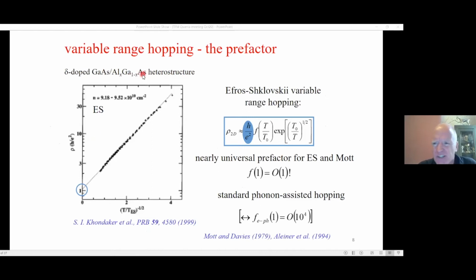And just a little bit more detail on that. If we're in this Efros-Shklovskii regime, and we normalize the temperature to the characteristic temperature for each carrier density and then plot them out, they have a universal behavior. They all fall on the same line. The intercept is just h over e squared. Very interesting. Why should that be? It's thermally assisted. The phonon should introduce a factor of about 10 to the 4 in the prefactor, but the prefactor turns out to be just h over e squared. Very interesting.